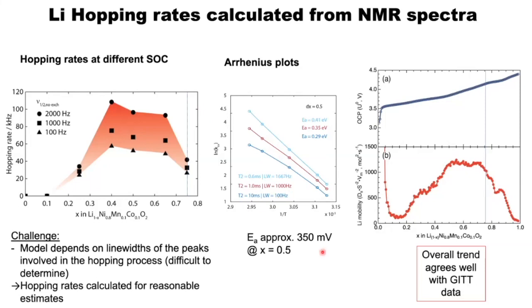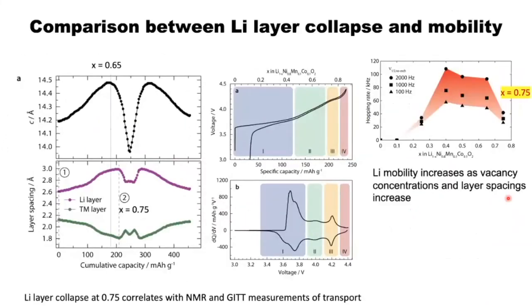modeling. But the bottom line is the activation barriers for lithium transport are of the order of 350 millivolts, which is very close to that predicted earlier on by the simulation or the DFT calculations of Gerbrand Ceder in this group. And the point also is that the mobility we get agrees very well with that obtained by GITT, where above about 0.75, you get a rapid decrease in the lithium mobility.